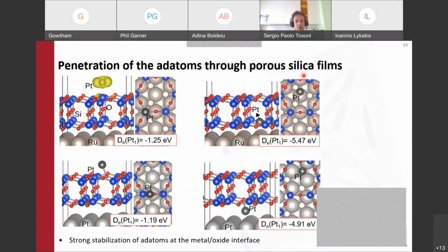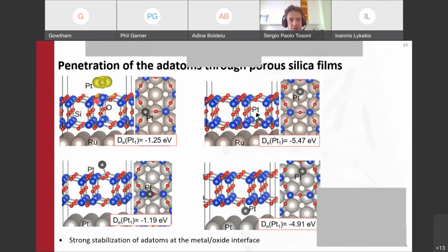Then we explore a further aspect while focusing on the silica bilayer film. This is a porous structure. If you look at the top view here, there are these hexagonal rings, and atomic species may want to permeate through the ring and go to the interface between the film and the metal substrate. And we tried this for platinum atoms on silica bilayer supported on ruthenium or platinum. As you can see, in both cases we have a strong increase in the adsorption energy if the platinum species can penetrate through the film and go to the interface.